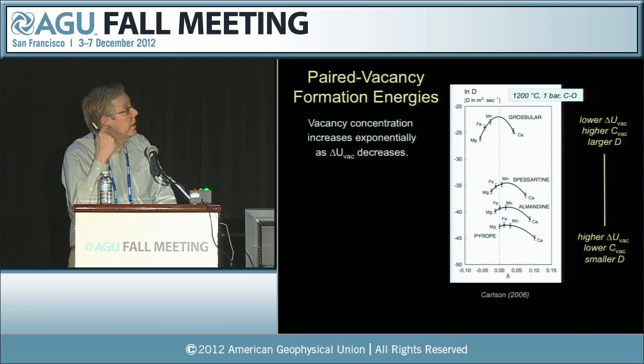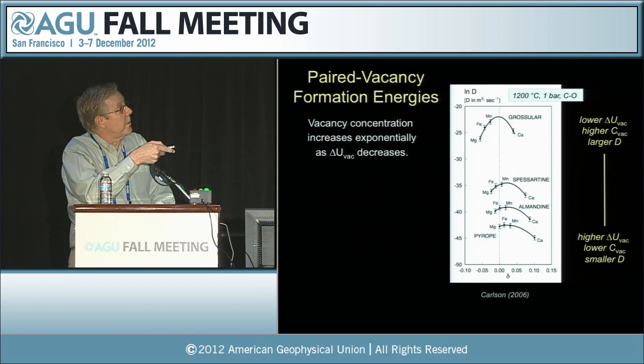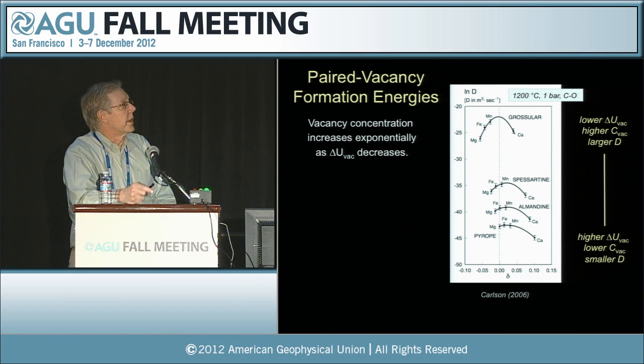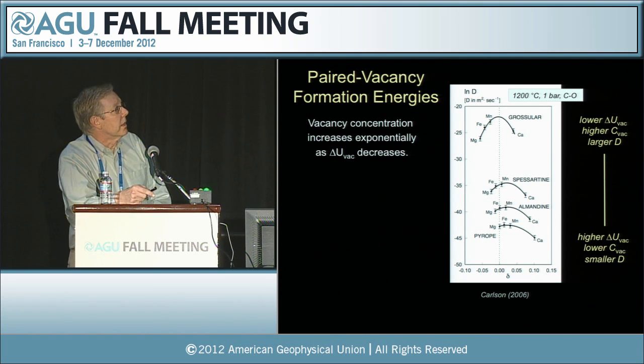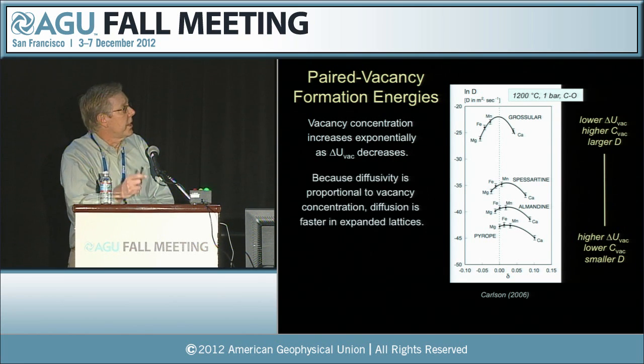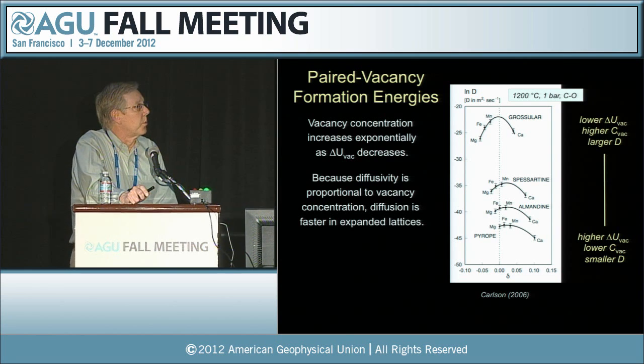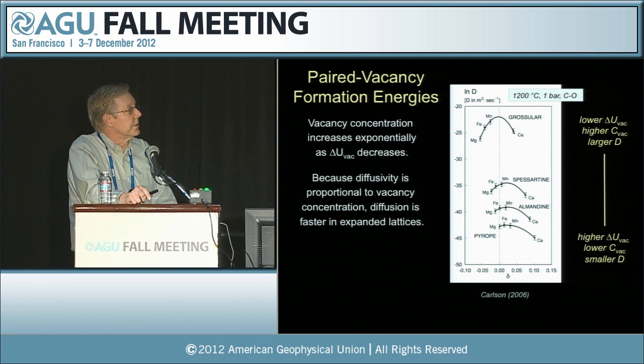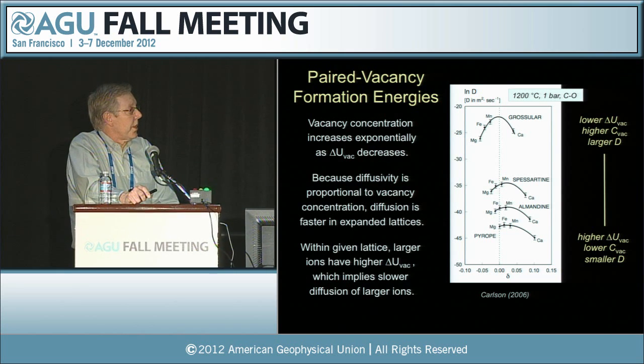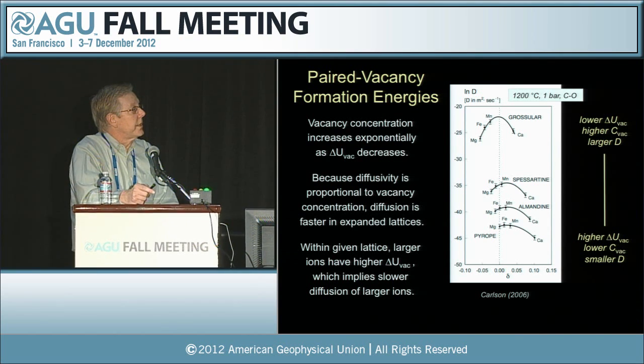And these have very important impacts on the diffusion, because we know from thermodynamics that the vacancy concentration increases exponentially as the vacancy formation energy decreases. So over here in Grossular, where we have a lower vacancy formation energy, we have a higher concentration of vacancies, which produces a larger diffusivity, and the opposite is true at the other end of the scale. And because the diffusivity is proportional to the vacancy concentration, that's why the diffusion is faster in these expanded lattices. Note also that within a given lattice, the larger ions have a higher vacancy formation energy, and that implies slower diffusion of larger ions.